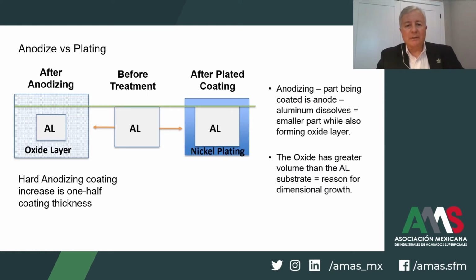In comparing anodizing versus plating, the creation of the anodic oxide layer actually involves dissolving the aluminum while also creating the oxide layer into the aluminum. This is much different compared to plating or a conversion coating that provides a coating over the aluminum. The oxide also has a greater volume or dimensional growth. So both types of mechanisms work: dissolution of the metal, then growth of the oxide, which is important for the part dimension. If you have to worry about reworking parts, the stripping and rework of poor quality anodized parts has many dimensional considerations. So getting the anodizing process right the first time is a critical success point of doing the process properly.